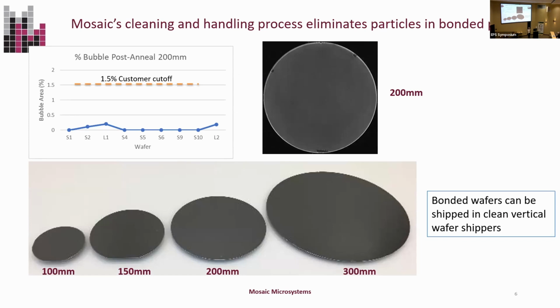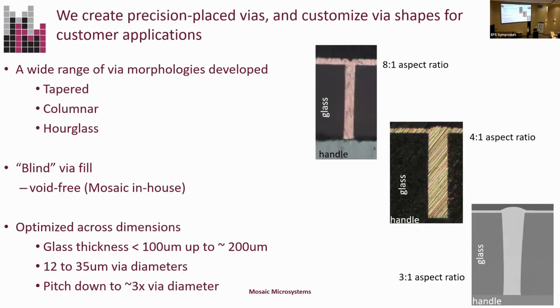particle free bond. So what I'm showing you here is our initial spec for ourselves was about 1.5% of the area of the wafer. We wanted the bubbles to be less than that. A very small particle can give rise to quite a visible bubble, optically easy to see, that may not actually be a problem for processing, but certainly is a PR problem. So we learned how to actually make sure that our bubble density stays very well below our spec.